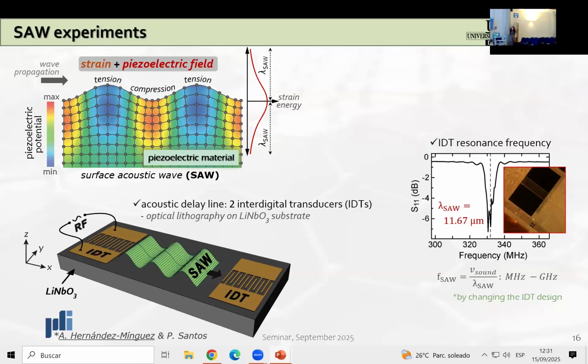So now that I've described the samples, what we wanted to do is find a way to control different properties of these systems in real time. And this can be done using the strain and piezoelectric field of an acoustic wave that is propagating along the surface of some piezoelectric material. So in our case, we use such an acoustic delay line, which consists of 2 interdigital transducers that we lithographically pattern on the surface of a lithium niobate crystal.